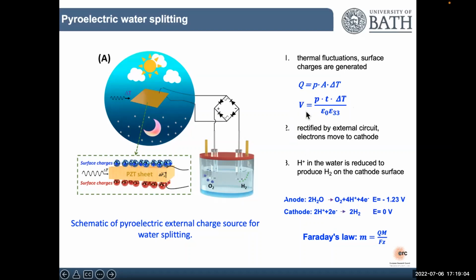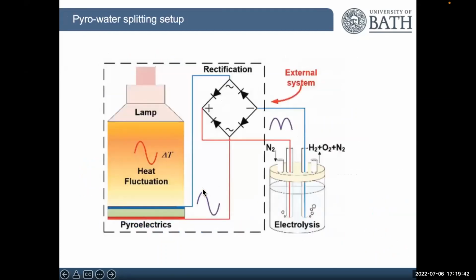So I can tune the material and the geometry to generate 1.5 volts, but also I need to maximize the amount of charge. And well, that equation here, so I can maximize maybe the pyro coefficient, the change in temperature, or the area. So again, surprise, surprise, the charge is proportional to area, because it's that surface charge that I'm using. So there's a balance here. I need the 1.5 volts to get the reaction going, but I also need the charge to maximize the amount of hydrogen I'm producing.